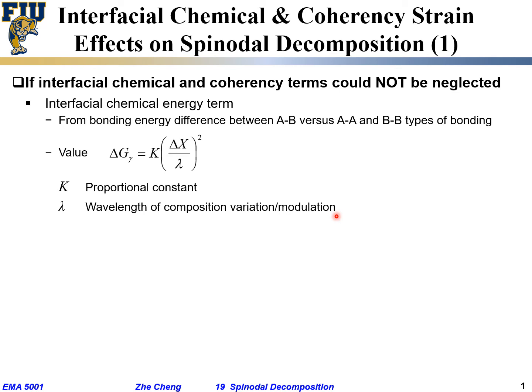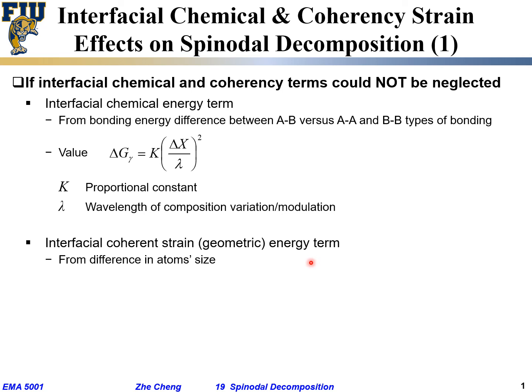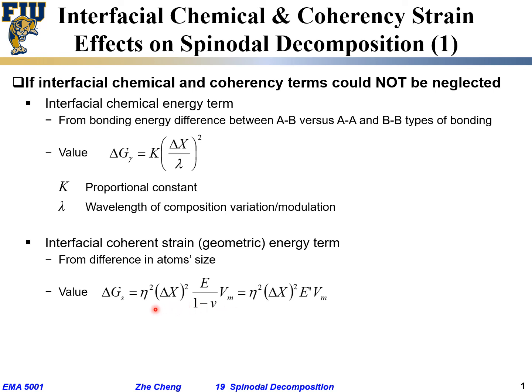In addition to the chemical term, there is also a coherency strain energy term. No matter how close different elements are, there is always some minor difference in atom size, which causes a geometric or coherent strain. For simplicity, this coherency strain-related interfacial energy — written as delta G_s — is expressed as eta squared times delta x squared times Young's modulus divided by one minus Poisson's ratio, times the molar volume.